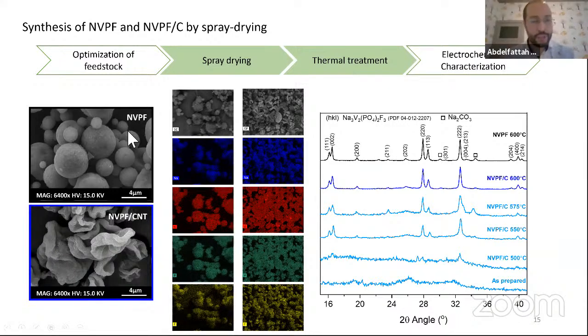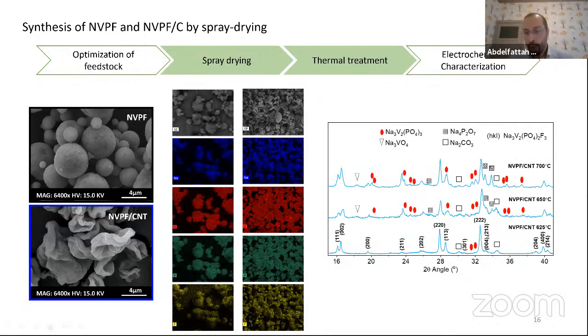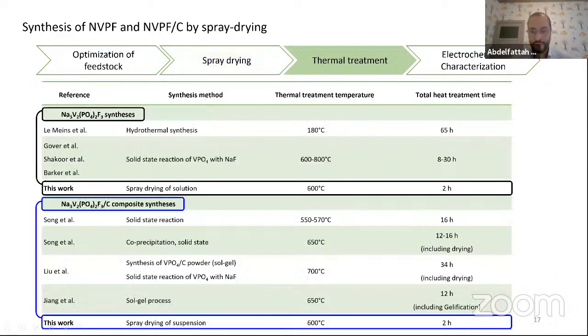But the main difference between the material with and without carbon nanotubes is that with carbon nanotubes, we have this flower-like morphology, but without carbon nanotubes, we have these nice spherical particles, which means that the addition of carbon nanotubes has a great effect on the morphology of our NVPF material. When we go up in temperature to try to increase the crystallinity of the NVPF material, we can see that we have some degradation of the material. So we stop the calcination at 600 degrees.